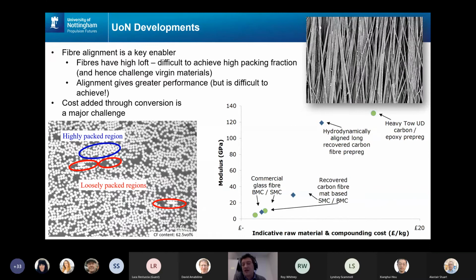So we've developed a process here that disperses the recycled fibers in a liquid, and then we use a hydrodynamic effect, a sort of convergent flow process, to realign the fibers and make them look a bit more like this in top view, or this in side view. So we're looking at fiber alignment not really to get higher performance in this direction than the transverse direction, but to get higher packing so that we can get more of these fibers into our composites. But cost and energy and labor added through that conversion process are a big challenge.